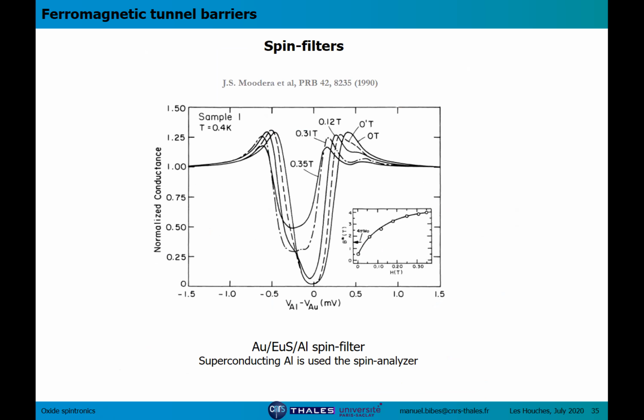So the first demonstration of spin filtering with ferromagnetic barriers was again given by Moodera, and he used the Meservey-Tedrow technique. So again, using superconducting aluminum as a spin detector in the magnetic field to induce Zeeman splitting. And europium sulfide was the ferromagnetic insulator. There's a number of ferromagnetic insulators in the europium chalcogenide family. Europium sulfide has a TC of 16 Kelvin. There's also europium oxide, which has a TC of 69 Kelvin and was used later by Moodera as well. And here the other electrode is gold.